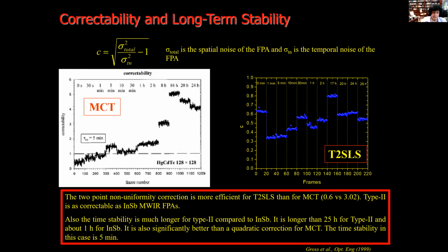Now, one of the very important things that we demonstrated was part of the PhD of Pierre Delaunay. The material and the focal plane arrays went through MIT Lincoln Lab and the Lockheed group, and they demonstrated in the system the correctability and long-term stability, comparing mercury cadmium telluride, the type-II focal plane arrays at 9 micron, 10 micron, and indium antimonide. They demonstrated that the two-point non-uniformity correction is more efficient for type-II than for mercury cadmium telluride, and the stability is much longer for type-II compared to indium antimonide.